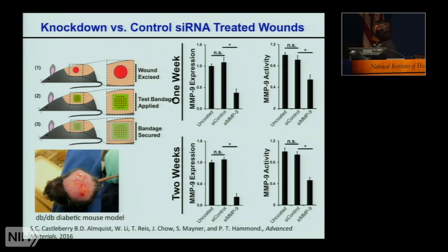If you look over time at the gene expression in these animals, at 1 week and at 2 weeks, we were essentially designing these systems to be active over a 14-day period. What we're seeing is a knockdown of MMP9 in the wound of 60% at 1 week and 85% at 2 weeks, which is significant, especially given that these are unmodified siRNA. We also see a corresponding drop in MMP9 activity.